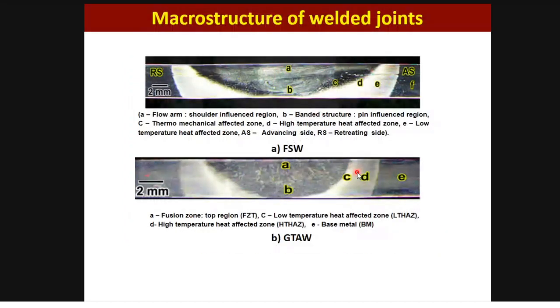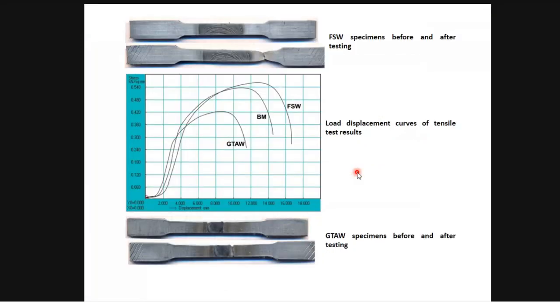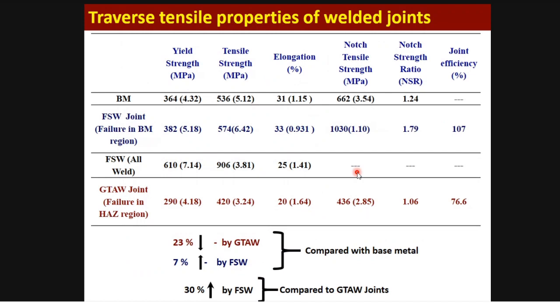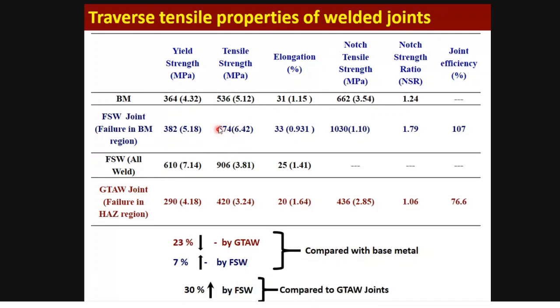Let's see the macrostructure. You'll find a lot of difference in the macro itself. Again, I think it's a 3 mm thickness. And the tensile test was conducted on the specimens. In the FSW joints, you see that the strength is very high and the ductility is also better than the TIG welded joints. The values are given in this table. The tensile strength of the base metal is 536. The FSW joint, a transverse tensile specimen extracted in the transverse direction, is 574. It's higher than the base material.